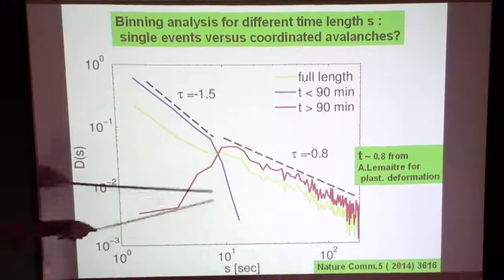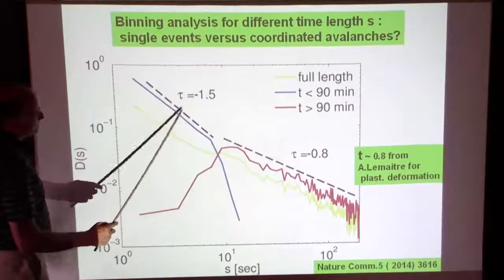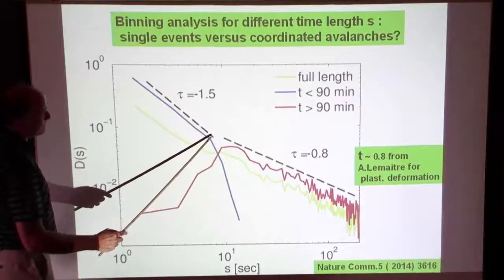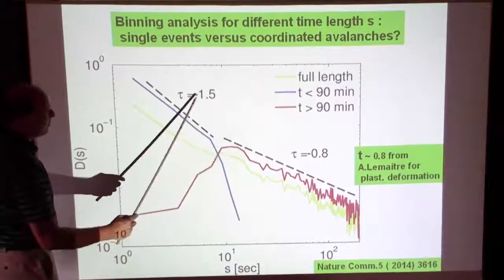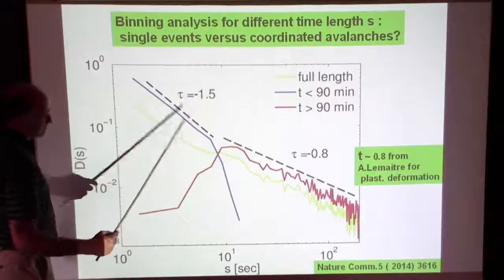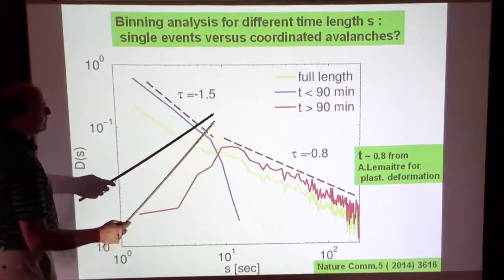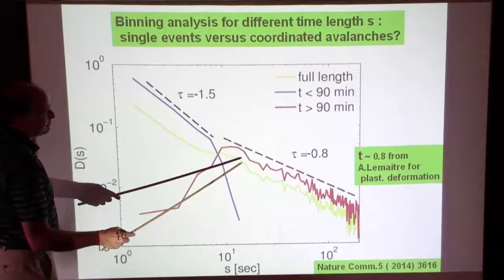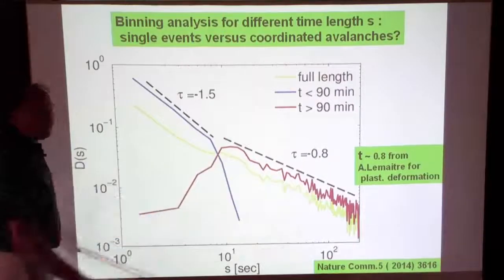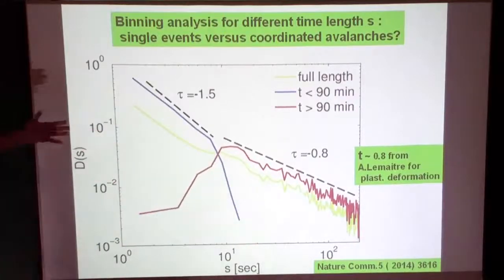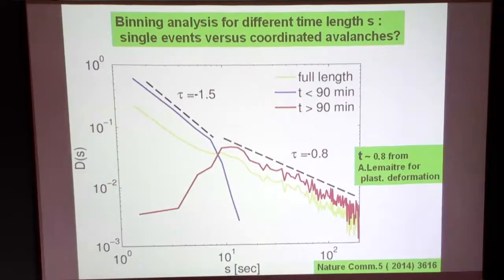He discussed that for the earthquakes. There is a change in the power law from the normal one, which is the mean field discussion we had so often here during the last couple of weeks, to a very different one, which Alain Lemaitre tells me is a shear band, then, but unfortunately he's not here. So are you saying if you actually look at what happens to the sample, can you start seeing the shear bands after 90 minutes? Well, we have no tools for doing that.